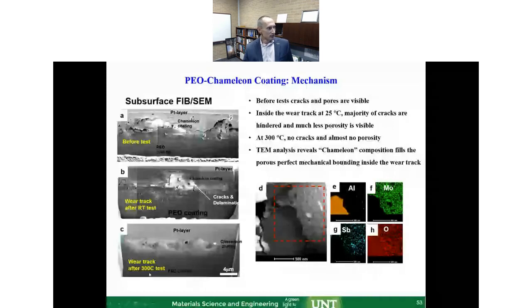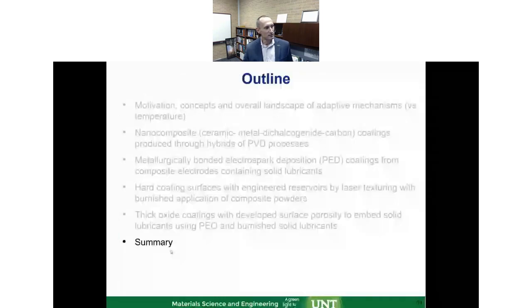And then with the test at room temperature, we can still see them, right? But once we run at 300 C, it gets so much more uniform. We don't see much of the porosity. I definitely don't see any cracks. So almost like a self-healing effect in here. So we think that at this temperature combination and pressure from the wear, we are forcing the chameleon composition inside of this porosity and cracks, and the material actually becomes denser, and therefore that provides better lubrication and reduced wear.